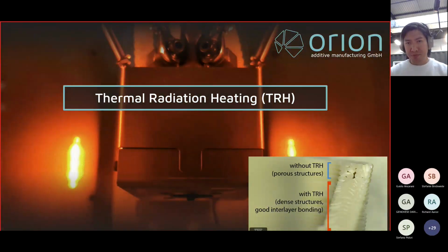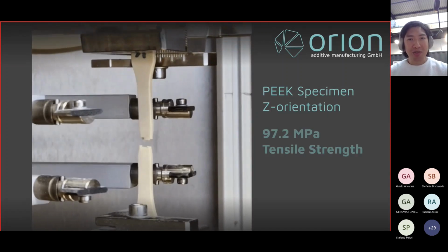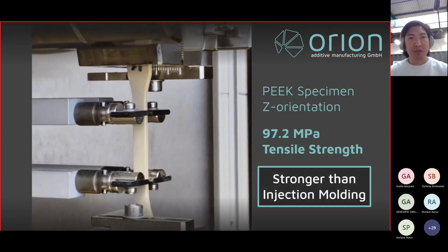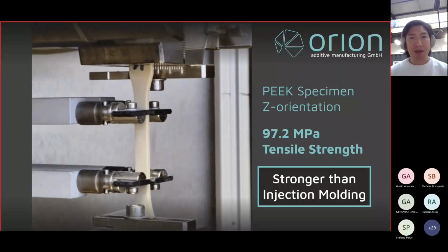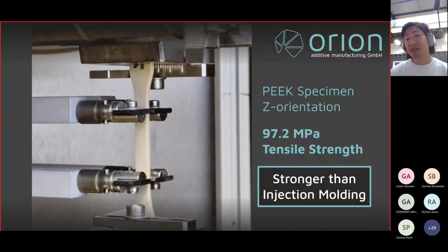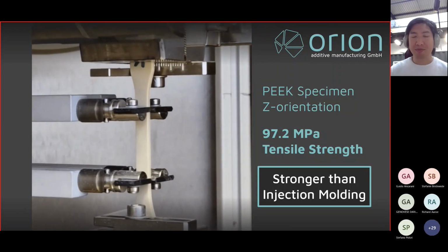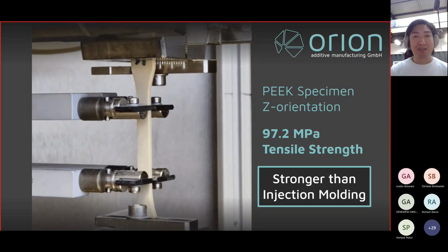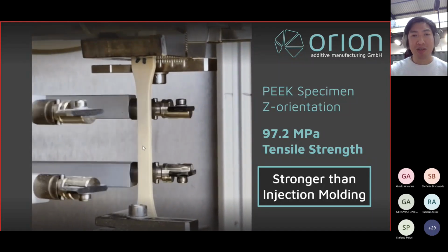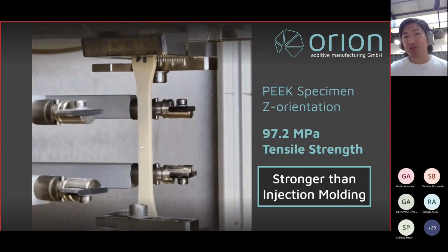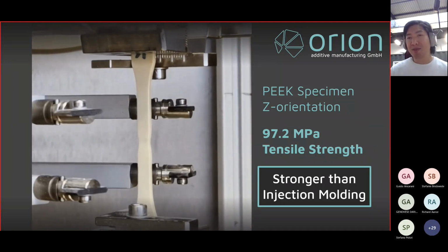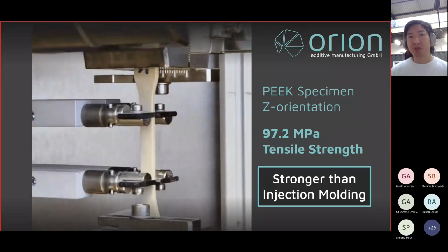So we've tested this technology. What you see here is actually a vertically printed tensile test bar. And as it's being pulled, you can actually see it beginning to stretch. And it's a characteristic that we call necking. So you can see it starts to slim out in the middle section here before it breaks. This is what you would expect from an injection molded part. But this is actually a 3D printed part. And not only is this a 3D printed part, but this is also oriented in the weakest direction that you would normally expect a 3D printed part to behave.